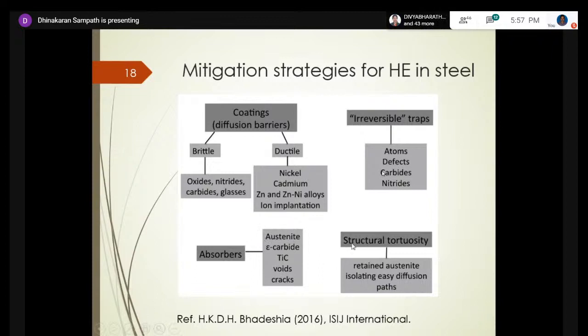Then structural tortuosity: they introduce low diffusivity phases in ferritic steel. Ferrite is BCC, so it will have high diffusivity. They design the alloy in such a way that diffusion does not take place continuously. They create a kind of maze, which will not allow the diffusion to happen as needed.